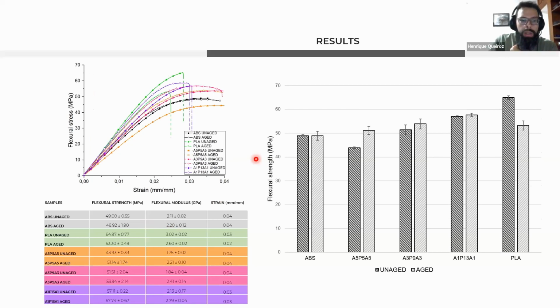So when we look at the flexural properties, first of all, we look at the behavior and we see a different story, right? So the behavior is not as exact for all cases. It still is for ABS here, but for the other specimens, it varied more significantly. Now, the reason for this most likely is because when you're under 3-point bending stresses, right, you have your maximum compression at the top and your maximum tensile stresses at the bottom. So the outer layers are the ones that are doing most of the work under the 3-point bending loads. And of course, the outer layers are also the layers that are going to be more affected by the aging in the marine environment.